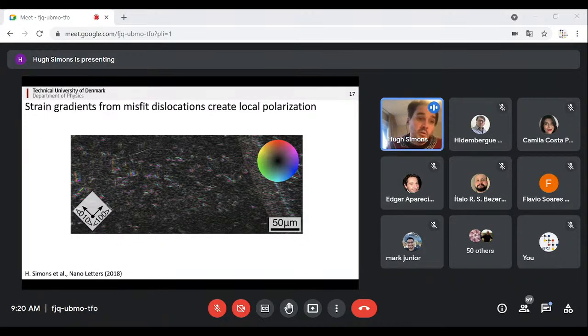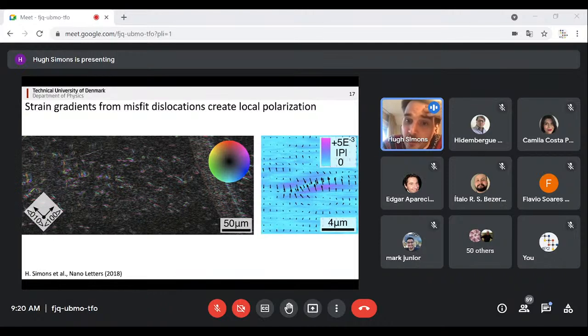And what's really interesting is because we can visualize the strain and the misorientation, it gives us a chance to see how the lattice is deforming. And because bismuth ferrite is, in principle, an insulator, when you apply a strain gradient to an insulator, you cause something called the flexoelectric effect, which is essentially an induced electric polarization due to the distortion of the lattice. And because we know what the strain gradients are, because we measure them and we also measure the misorientation, we can actually characterize what this flexoelectrically induced polarization should be. If you look at this, which is the flexoelectrically induced polarization vector around an individual edge dislocation, you can see that they point to each other in a head-to-head formation. This implies that just due to the deformation of the lattice, these edge dislocations should be reasonably charged, actually.